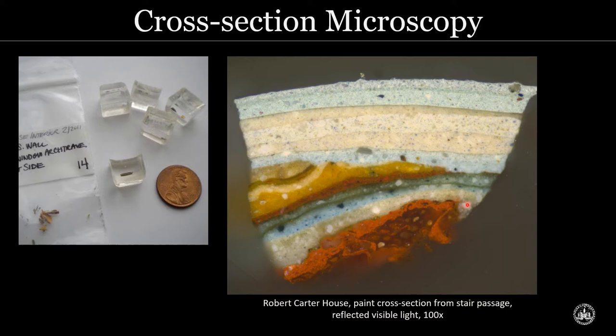And another interesting piece of evidence in this sample is the way that the natural stratigraphy of these early paints is kind of abruptly cut off here. And that's something that we typically see when paints have flaked and then been scraped down over time, and then these modern paints have been applied over that. So this technique can tell me a lot about the number and the nature of layers. So it's a lot more than just telling me what the very first paint color was. So that's just the tip of the iceberg of the information that I can gather from a paint cross-section.